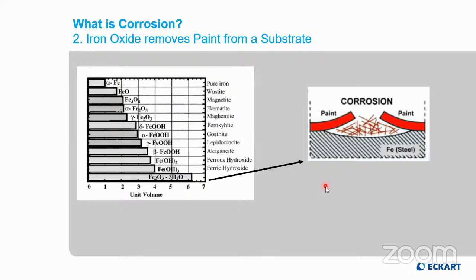Chemically, rust is iron oxide hydrate. And from this graph, which is relatively unimportant, you can see that rust is a very voluminous species, the most voluminous species out of all the iron oxide species. And because rust is so voluminous, it can penetrate between the steel substrate and the paint film, by that removing the paint film from the substrate.